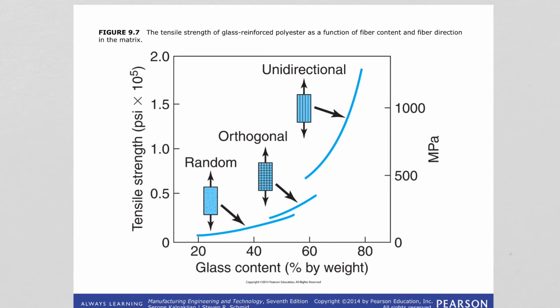And this figure shows us that. Okay, so here we see tensile strength versus the glass fiber content, and we see how the enhancement is achieved based on the alignment. The best performance we obtained when we align the fibers in only one direction, we call it unidirectional, and when we test the material along the direction of the fiber, that's when we obtain the best strength values.